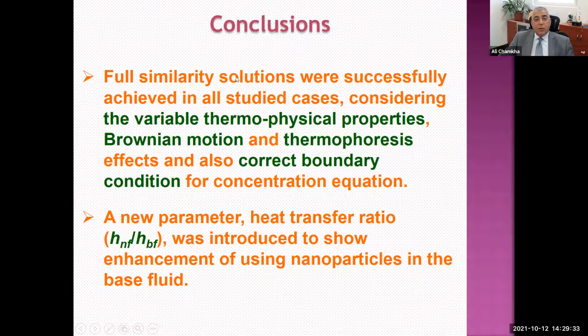Okay. Conclusion. In conclusion, we found full similarity solutions were successfully achieved in all studied cases, considering the variable thermophysical properties, Brownian motion, and thermophoresis effects, and also correct boundary conditions for the concentration equation. A new parameter, heat transfer ratio, we developed. Heat transfer coefficient of nanofluid over heat transfer coefficient of base fluid was introduced to show the enhancement of using nanoparticles in the base fluid.